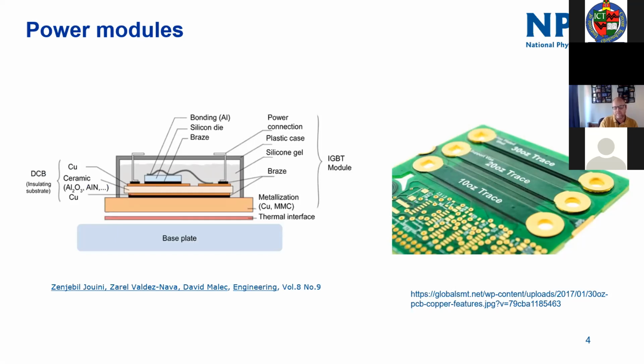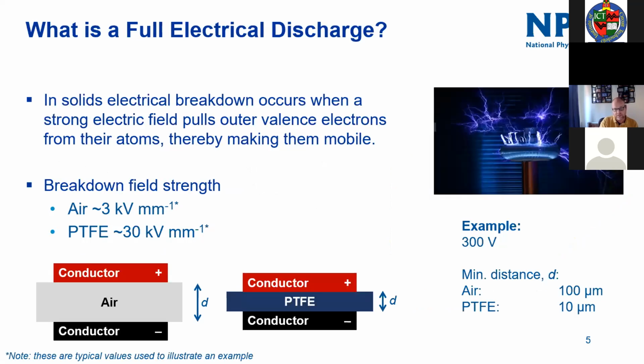these structures. But there are reasons why people use ceramics in high voltage work, and that's to a large extent dictated by electrical discharge within the systems. So I'm sure we're all familiar with a full electrical discharge that happens in air at around 3 kilovolts for every millimeter of spacing you have between conductors. If you put a dielectric between those, PTFE for instance, you'll push that up to about 30 kilovolts per millimeter. And when it does break down, there's obviously a lot of flash bangs and wallops going on.